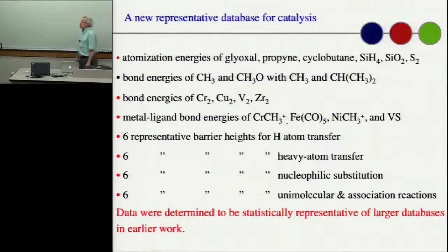So one of the things we did was we made a new database for catalysis. I mentioned that we have a lot of data in a lot of databases. We did statistical analysis of these data. And we found smaller databases that were statistically representative of the larger databases. So for example, whatever your mean error is on those bond energies tends to be your mean error on a much bigger set of transition metal bond energies.